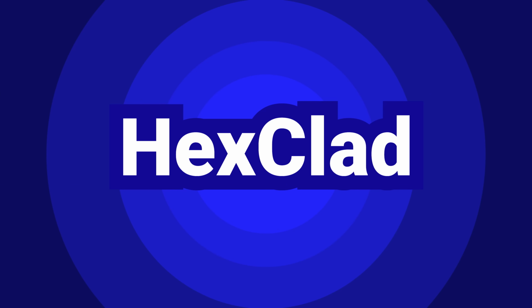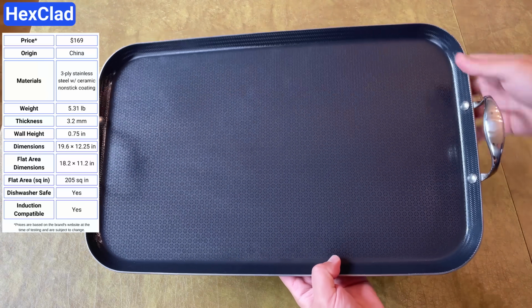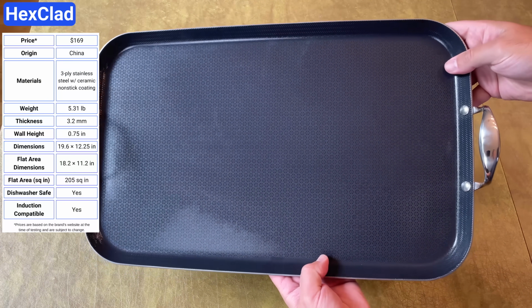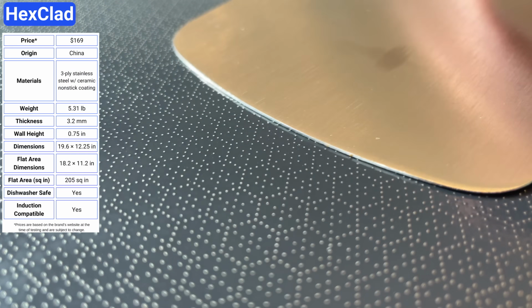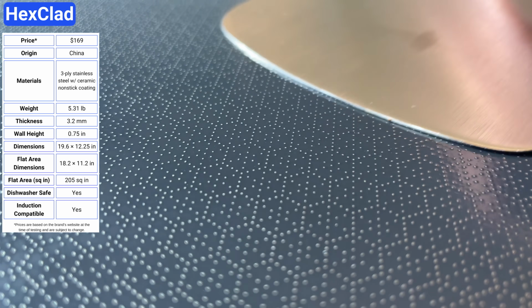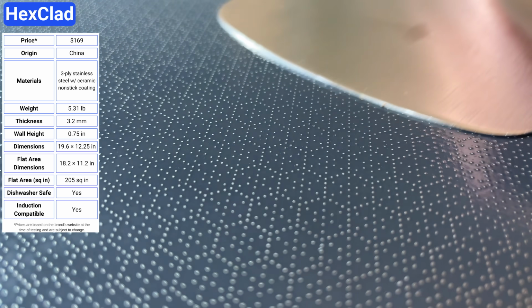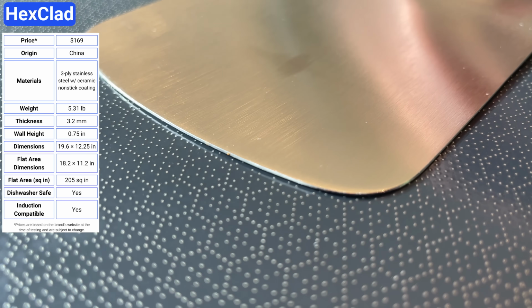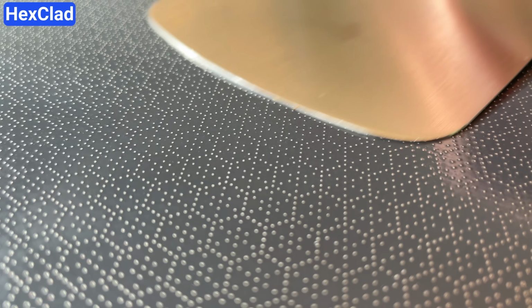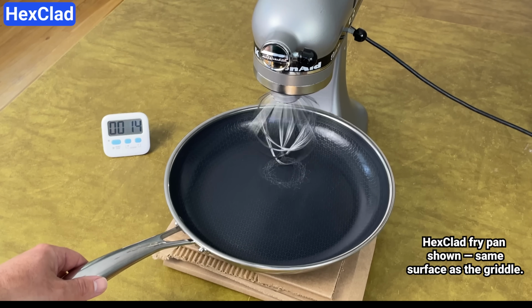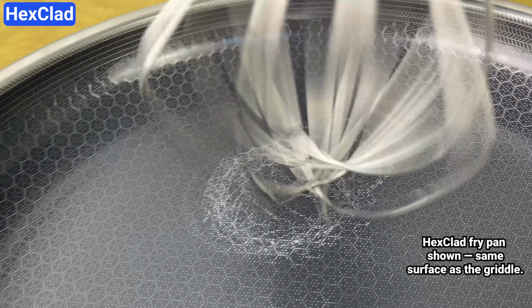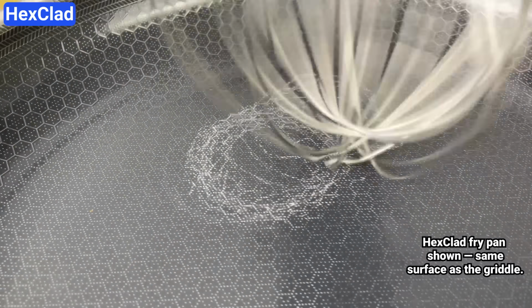cheap. The HexClad griddle is made of 3-ply stainless steel with HexClad's signature hybrid surface. The idea behind the hybrid surface is that your spatula glides along the raised stainless steel instead of scraping directly against the ceramic nonstick coating underneath. I stress tested it, and while the steel does provide some protection, there's still plenty of space between the ridges for the coating to get scratched.